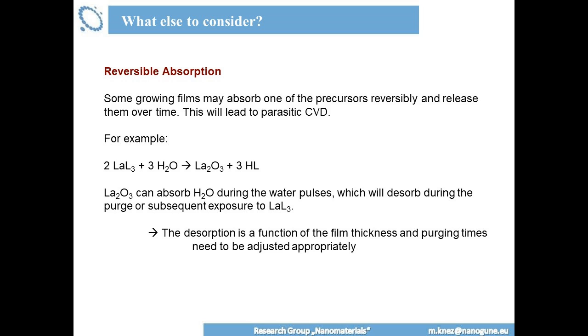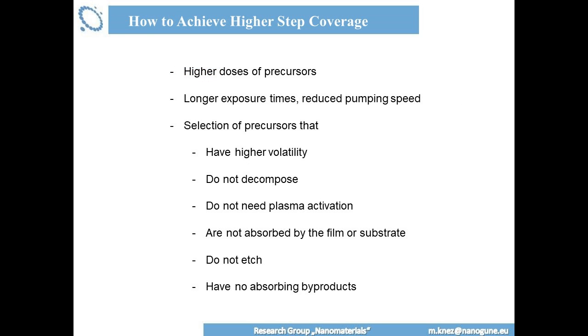You need to also consider this because in this case also you will have a non-ideal situation for the growth in, for example, pores. No matter whether you have your diffusion times adjusted properly, you will still have these issues. So, if you want to have a high step coverage, not sure whether this will be the case in many of the projects here, but I think you will do some testing of the ALD or MLD in many situations, also in high temperature structures.